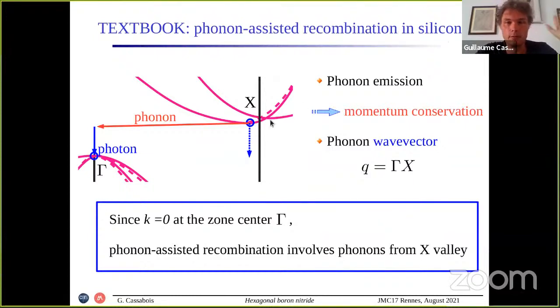In silicon, a cubic material, the valence band maximum is at the zone center, the gamma point, and the minimum of the conduction band is around the X valley. To fulfill momentum conservation, one needs the emission of one phonon and one photon. A very basic example of solid state physics.